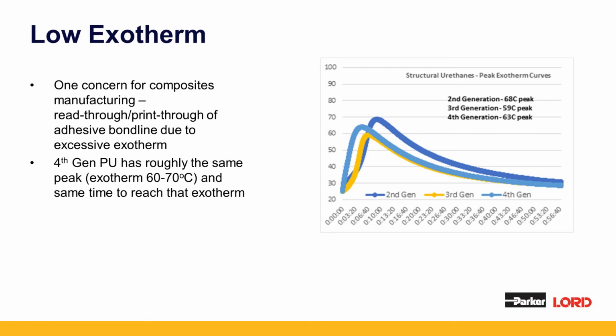So this is a concern with manufacturing. It's often called read-through or print-through. The 4th generation urethane, although it is a very fast urethane, has roughly the same peak exotherm of 60 to 70 Celsius, in that range, as the previous generation 2nd and 3rd. So there's no real concern here. Where the heat is generated is not necessarily correlative to a faster cure.